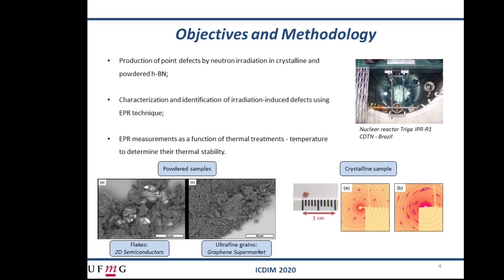Produce defects in hexagonal boron nitride using neutron irradiation, study the produced defects using electron paramagnetic resonance, and determine their thermostability by annealing experiments. The neutron radiation makes it possible that defects can be produced in a controlled way. The concentration of the defects is proportional to the radiation dose. In addition, particle radiation is more likely to produce vacancy-type defects, which gives us greater control over the types of defects produced.